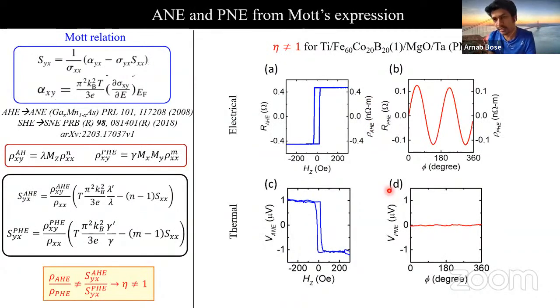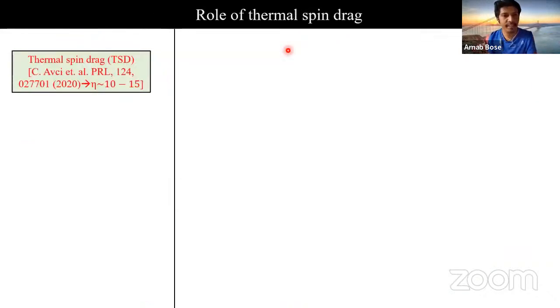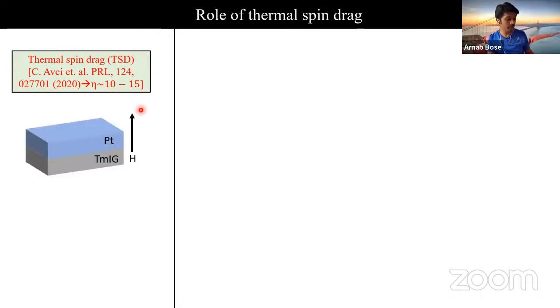So that is the justification that we made, that the conducting or semiconducting proximatized magnet at the interface of TMIG and platinum could lead to substantial deviation from 1. There is also a recent report studying this same effect in TMIG platinum, in this particular work, where they have also reported the value of eta substantially different than 1, which is also in agreement with our experimental observation.